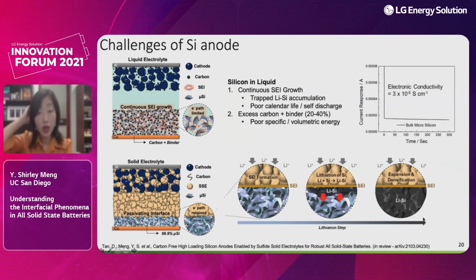This strategy should also work because we checked the electronic conductivity of pure silicon, not lithium silicon. The pure silicon's electronic conductivity is an order of magnitude higher than the solid electrolyte.